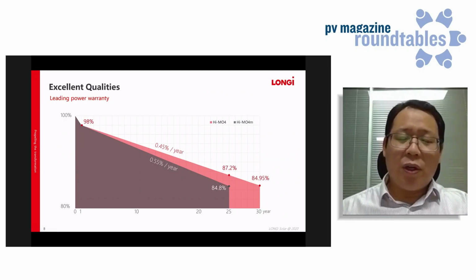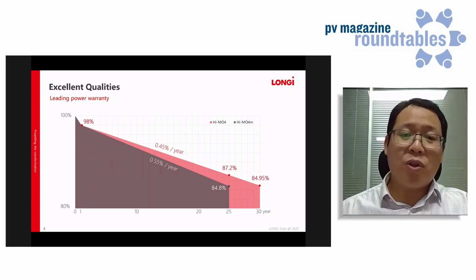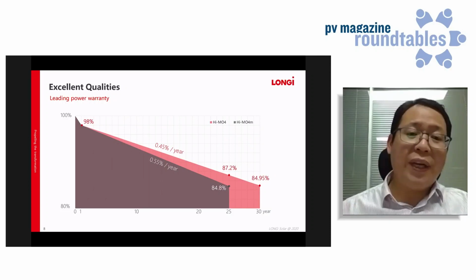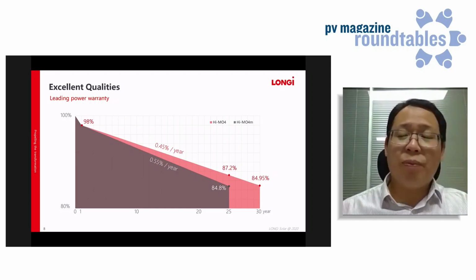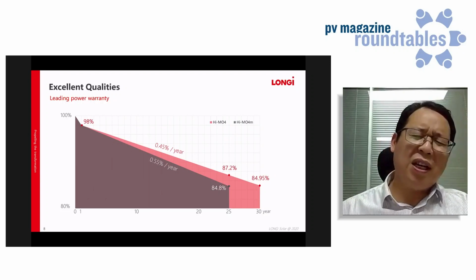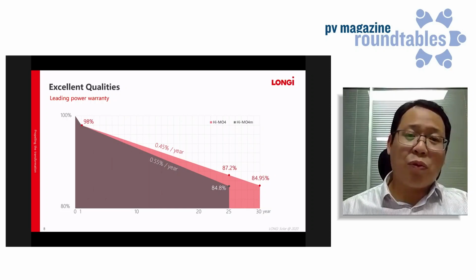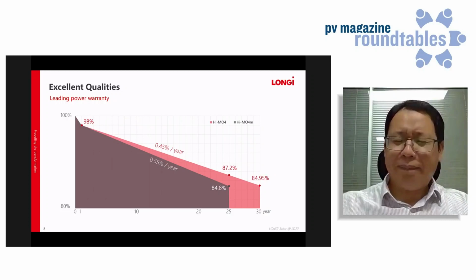All these results show that the gallium doped wafer has a very good benefit. So if we use gallium doped wafer, we can get a better degradation result. So we have a better quality warranty for the gallium doped wafer product. In the first year we guarantee the degradation is less than 2%. That's a quite good warranty in the industry.